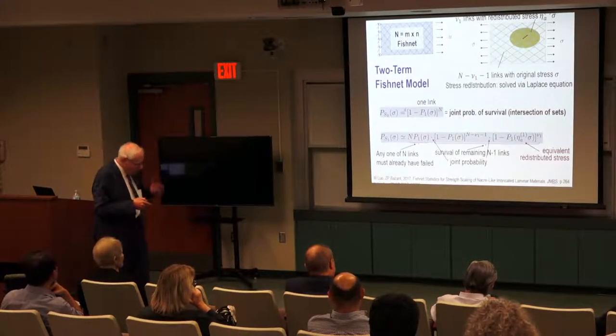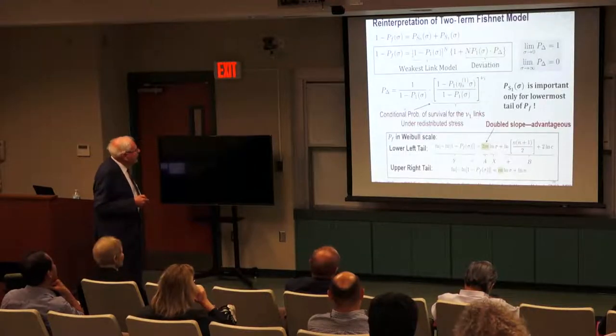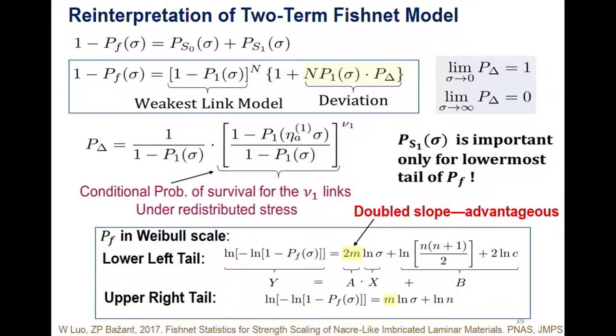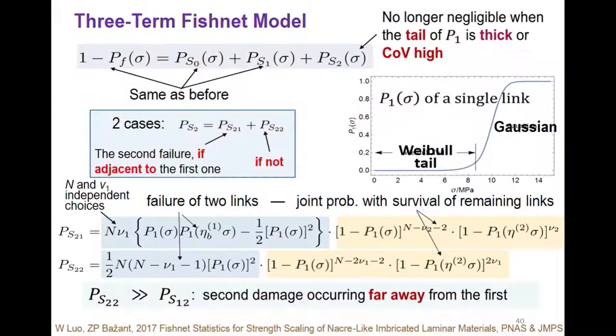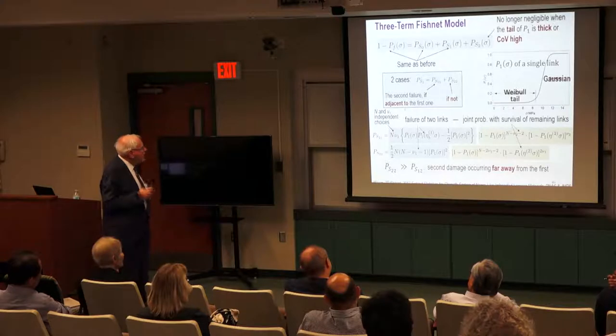So that's all calculated, and you can reinterpret it by putting it in the form of Weibull distribution with a correction term. This is the correction term, which is easily calculated, and so that's a second order approximation, we'll say, with two terms. With three terms, it's more complicated.